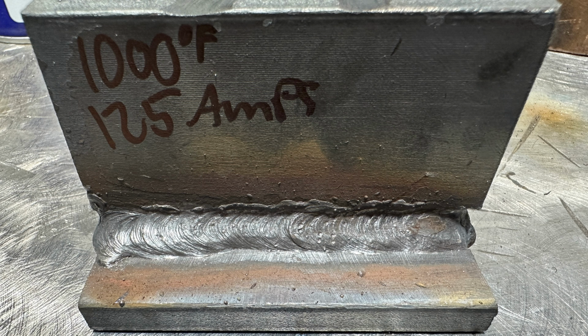So now this has one of the weirdest bead profiles I've seen. It's almost like a pear shape. So there's likely undercut at the top, but the bottom of the bead, it just slumps out a lot. And you'll see that in the cut and etch. But this definitely is not a profile that you want to see. It is overall flat, just rounder and fuller at the bottom than the top.